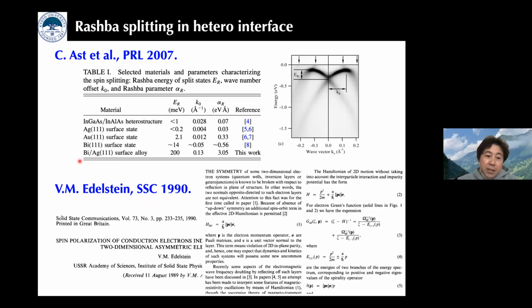And they fabricated bismuth silver alloys. And in that material system, they observed the gigantic Rashba splitting. So this table shows a comparison of the Rashba parameter alpha R, and you can see bismuth silver possesses gigantic Rashba splitting. Because the Rashba field is large, we can realize efficient spin conversion at the interface between such material systems. And this was originally proposed by Edelstein from the theoretical viewpoint.